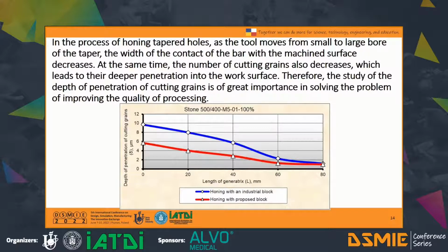The decrease in the penetration depth of the grains at the larger end of the hole is due to the introduction of additional supports, the optimal location of which was determined experimentally, which level the contact pressures.